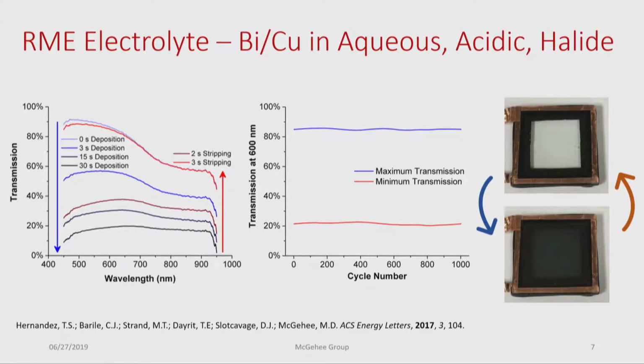After many trials and tribulations, basically running through the entire periodic table of every metal, we eventually concluded that the reversible electrodeposition of bismuth and copper is where we wanted to go. If you take a look at the devices here on the right, the reason this bimetallic system was so attractive is that we're able to produce a black, color-neutral absorbing film. At first glance, that's kind of surprising, because metals tend to be very reflective. But there's some really cool chemistry involved here that allows this bimetallic system to appear black and more absorbing rather than reflecting.